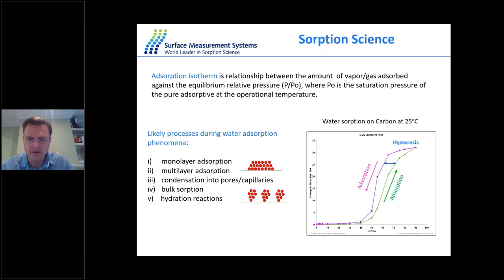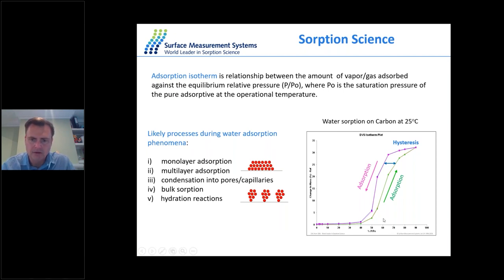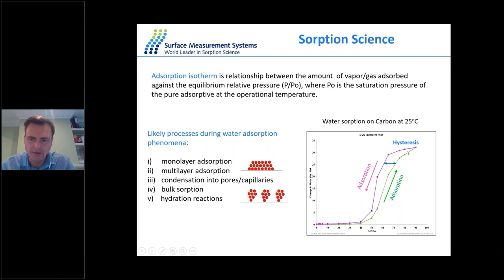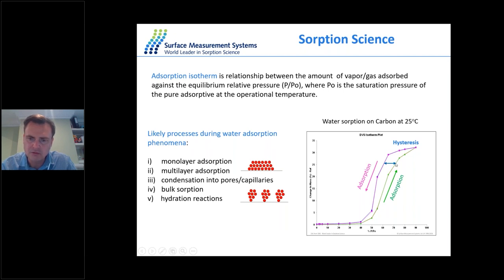On the x-axis we have relative pressure described as p/p₀, where p₀ is the saturation pressure at the adsorption temperature. On the y-axis we have the change in mass or amount adsorbed. During the adsorption process we step up the concentration of molecules, and as a result the amount of gas or vapor adsorbed goes up — the sample gains mass. On the desorption branch we step down the vapor concentration and the weight decreases. The gap between adsorption and desorption isotherms is called hysteresis.